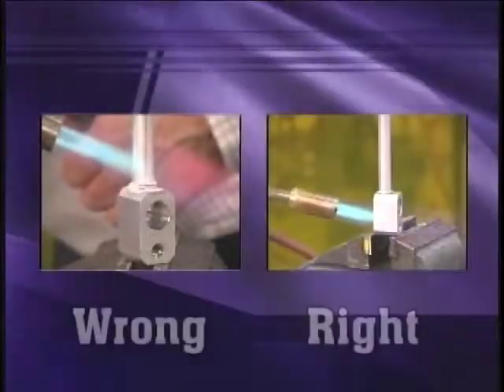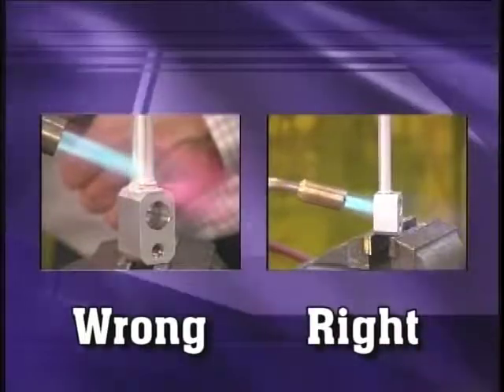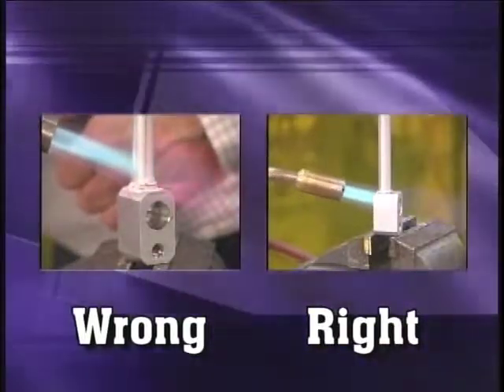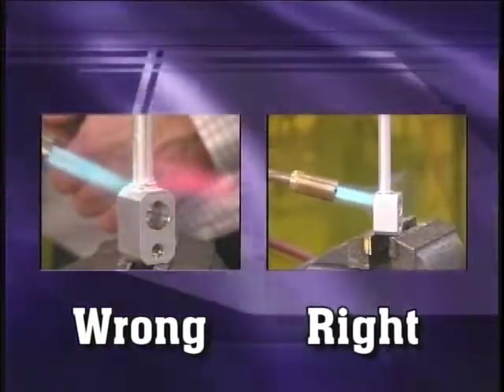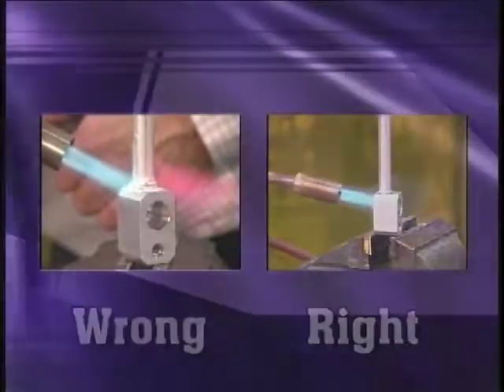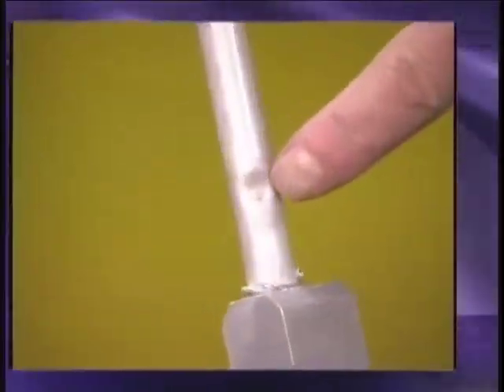Caution: when brazing a tube into a block, heat the block first and allow the conducted heat to heat up the tube. The tube has a lot less mass than the block, so it will overheat and melt very quickly under direct flame.